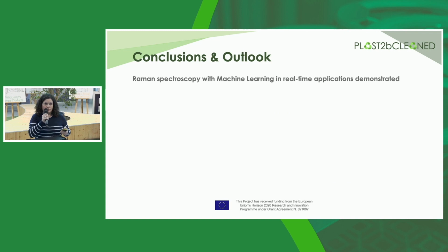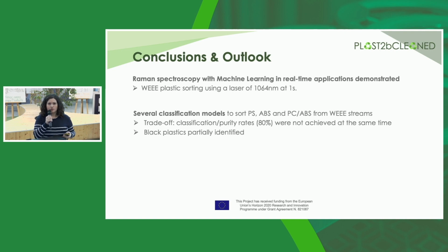So our main conclusions and results are that, first of all, as we have developed a RAMAN sorting prototype, we have demonstrated that RAMAN spectroscopy with machine learning techniques can be used in real-time application, in this case for WEEE plastic sorting. And the innovation is that we have used a laser of 1064 nanometer, acquiring a spectrum at 1 second. We have also developed several classification models to sort polystyrene, ABS and a blend of PC ABS from WEEE stream. However, as an overall result, we have obtained a trade-off between the classification and purity rates, as they were not achieved at the same time.